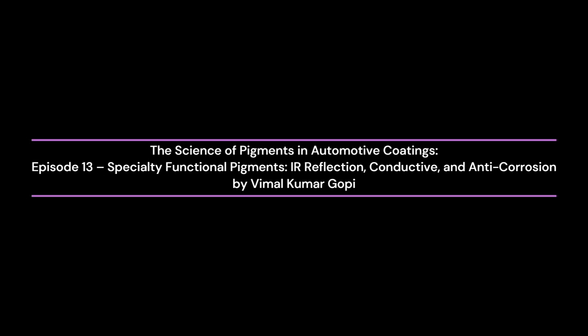Infrared reflective pigments include specially coated titanium dioxide, ceramic pigments, and metal oxide-based formulations engineered to maintain visible color, while selectively reflecting IR wavelengths. The effectiveness of IR reflective pigments depends on particle size, composition, and coating technology. For instance, core shell ceramic pigments are designed to optimize the refractive index contrast, enabling reflection of IR radiation without significantly altering visible color. Particle morphology, surface treatment, and distribution within the binder system are carefully controlled to balance heat reflectivity with gloss, hiding, and application properties.